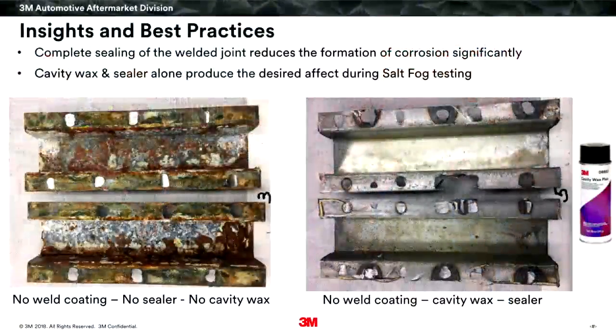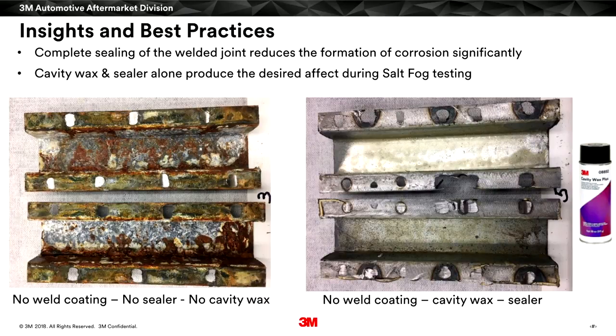Right. So let's talk about some best practices. This kind of goes back to what we saw from Chrysler, where they're saying don't use anything in those flanges when you're welding things together, but use cavity wax. Now, if you look on the left-hand side, this was a combination of MIG plug welding and spot welding. And that left-hand image, the number three rail, has nothing, no weld-through coating, no seam sealer, and no cavity wax. And on the right-hand side, that image has no weld-through coating, but cavity wax, and then seam sealer around the outer perimeter of the joint.